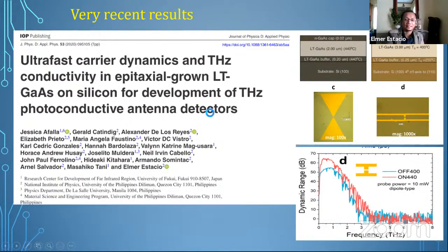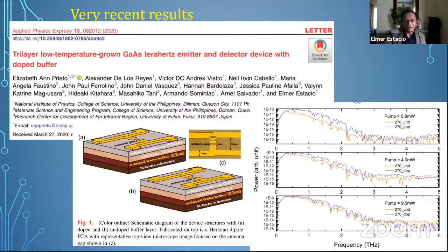We were able to successfully fabricate antennas using those substrates, and we were able to show very, very wideband terahertz radiation, having close to 7 orders of magnitude signal to noise ratio over a very wide frequency range of more than 3, almost 4 terahertz. This was published I think just this year, and we were able also to show our capability to grow novel multi-layers of gallium arsenide and show that we can further improve the terahertz radiation intensity of our photoconductive antenna devices. And this is very recent. I think this was accepted just during the start of the quarantine period here in the Philippines.